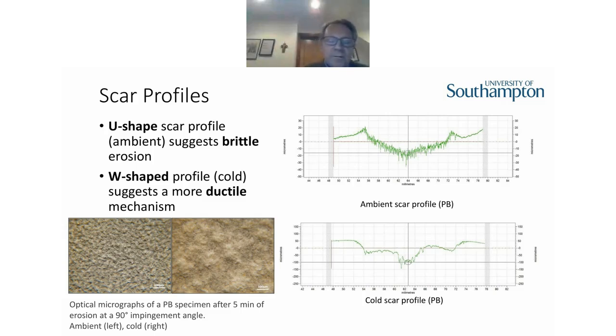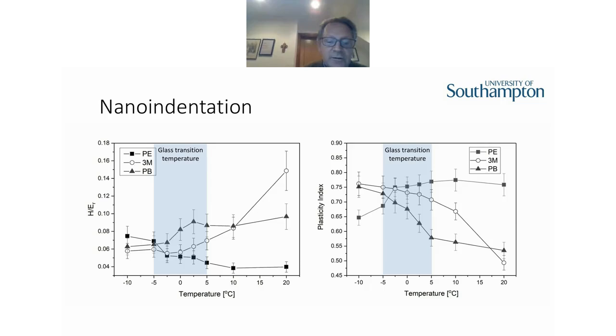If you then look at the surface profilometry, a U shape suggests slightly more brittle behavior perhaps, depending on the angle of particle attack, because you get a spread of angles. But if you go to the cold one, you get a much more complicated profile, some pitting and a sort of more W shape, showing us that we have a little bit more ductility and ductile process going on as you go colder, which was slightly unexpected. And you can see there's some optical microscopy here of what the surface looks like. So the mechanism of erosion is changing as you go down in temperature.